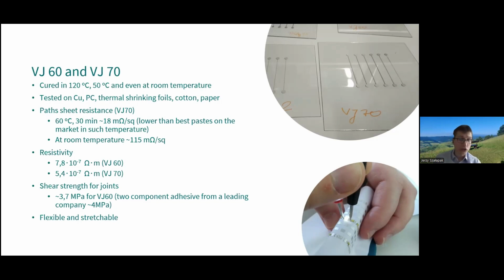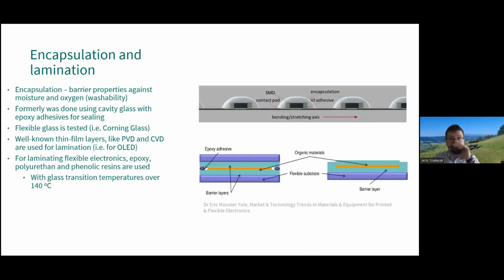So with Dr. Vitaly Szczenev from IZM Fraunhofer, we developed a formula for so-called VJ pastes that may be used for both paths and joints. The formula was tested on various substrates in various conditions. At 60 degrees, we were able to achieve a sheet resistance of 18 milliohms per square. That means that the resistivity of the layer is lower than that of the best adhesives on the market, well, at that point. Shear strength wasn't very impressive, but it was comparable to other materials like that. And it is flexible and stretchable.